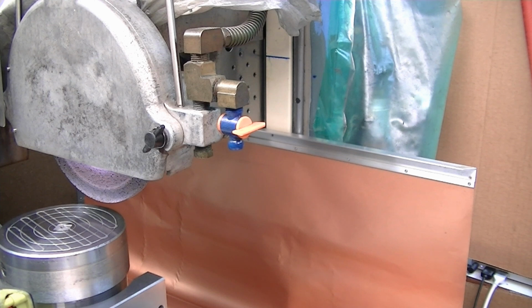One very important aspect of the precision grinding at this level and trying to get very good finishes and geometry at the same time is thermal growth of the column of the machine as it warms up. In my case, my grinder, the spindle runs hot because I have poor quality three-phase coming out of my phase converter. I have a VFD that I plan to put on, but at the moment it gets pretty warm, and that puts a lot of heat into the column until it settles out. It probably runs about 110 degrees. I have it fan cooled, but it still generates heat.